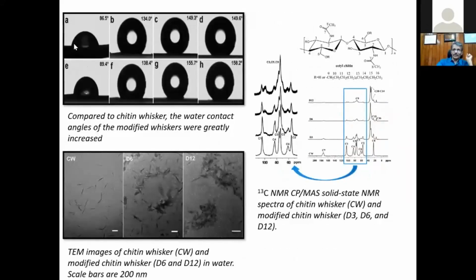Look at this slide. This is neat nanochitin, hydrophilic, contact angle 86.5. If you increase the number of hydrophobic groups, you see, dear friends, look at sample H. You can make superhydrophobic surfaces. The contact angle is 158.2. And dear friends, this is an excellent additive for oil. It's a positive modifier for oil or hydrophobic oil, and you can make excellent